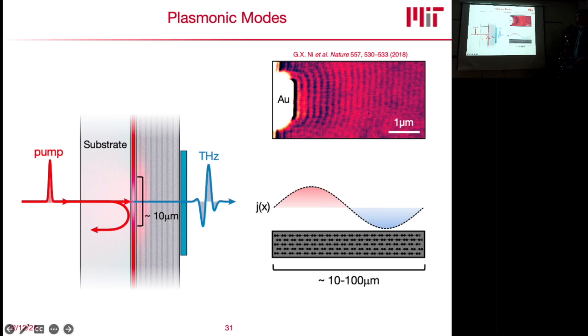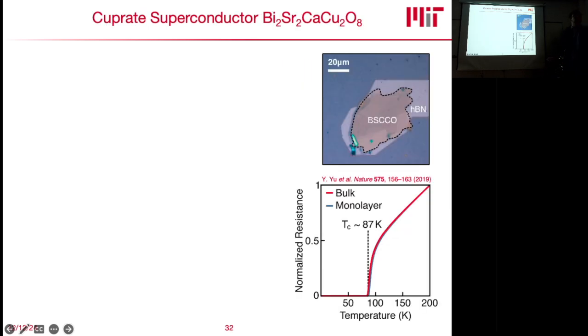this type of concept. And so we actually need to go now from a metal to a superconductor. Especially in the superconducting phase, you start creating a coherent ground state of the superconductor, which basically doesn't scatter. So you can now hopefully excite coherent motions of this suppressed-scattering ground state to create these plasmonic resonances. And for this, we worked with the group of Philip Kim at Harvard.